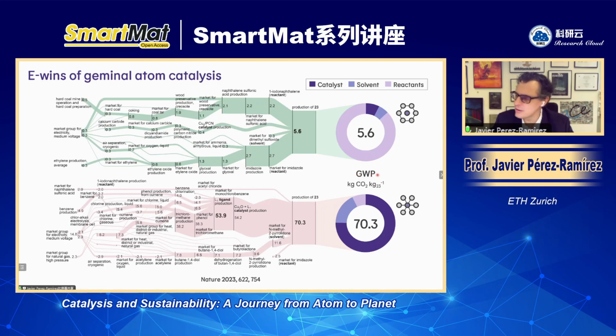And what you see is that the global warming potential is significantly reduced from 70.3 when we use the standard technology, homogeneous, to the geminal atom catalyst by 1 order of magnitude. It's important, right? And you see here the 5.6 and here 70.3. And now what you can see in this Sankey diagram is what creates this huge footprint of homogeneous systems. Well, you could just see the thickness of these lines, right? And this leads you to here. That's the thickest line in the production of the cross-coupling product using a homogeneous system. Where the biggest burden is in the production of the ligand for the homogeneous catalyst.